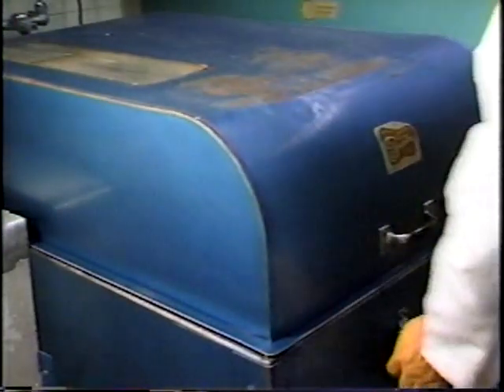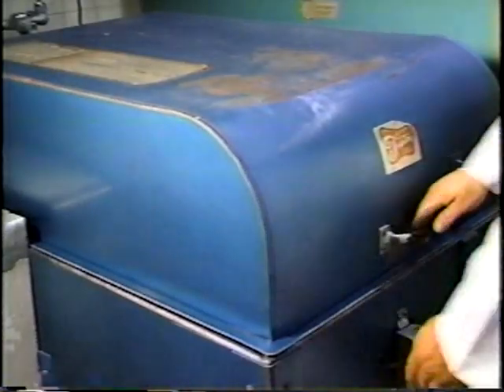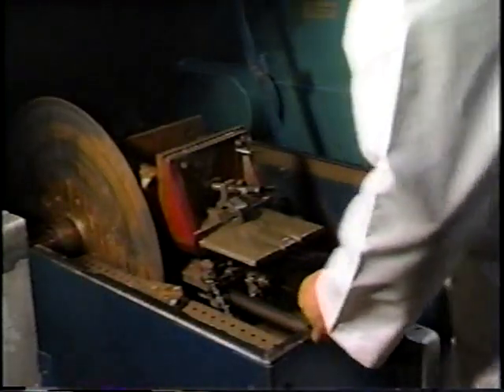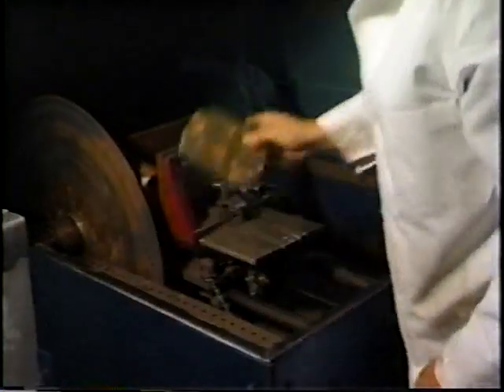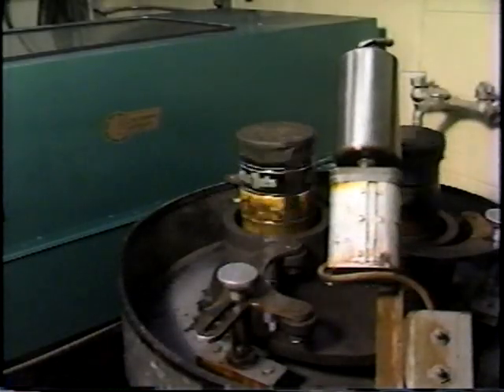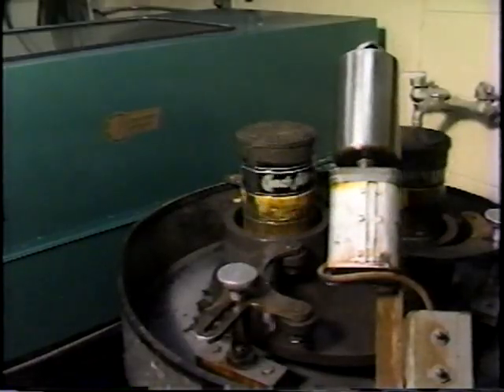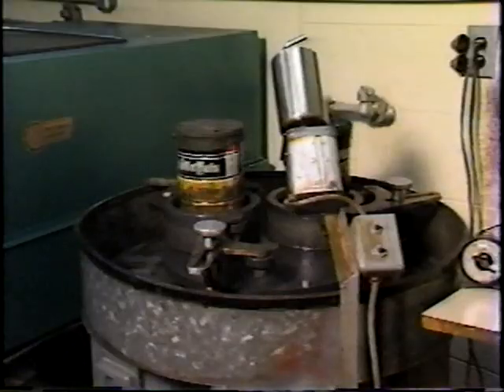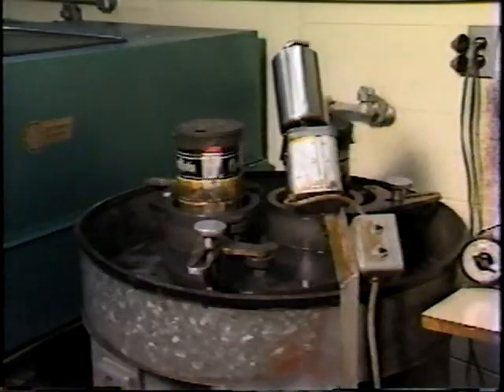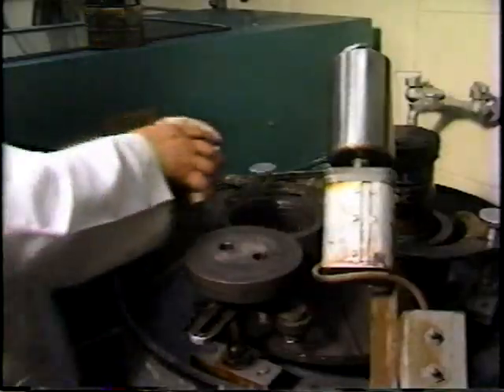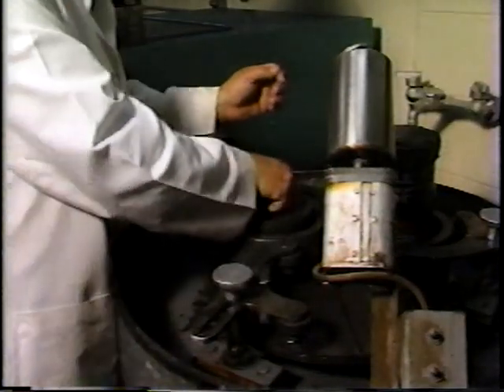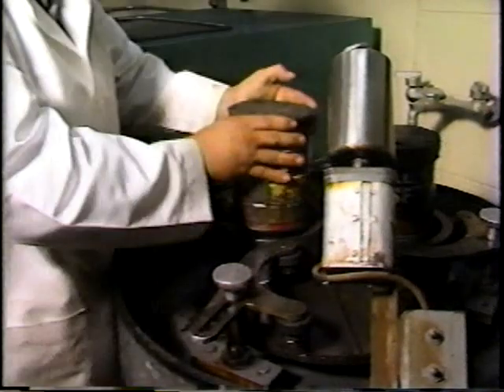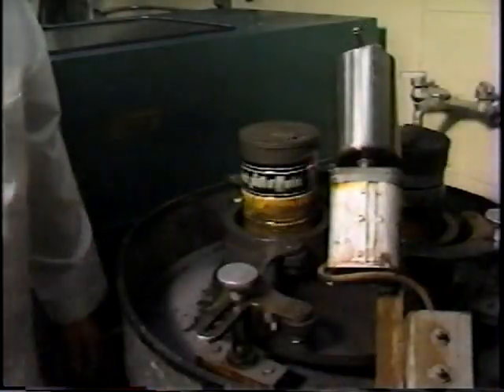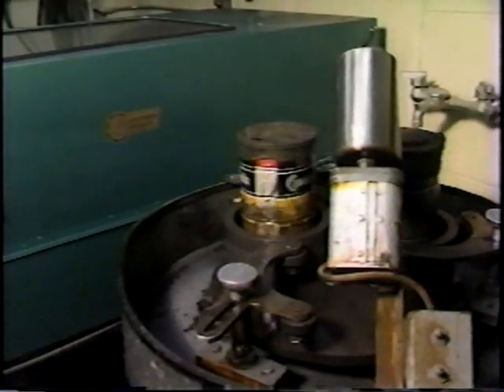For all types of petrographic examination, including air void determination, smooth slabs of concrete are cut on this large auto-feed diamond edge saw. They are then lapped on this semi-automatic equipment. We have 2 of these laps, one for the coarse grit and one for the fine. The specimens are placed inside these rings, which are held by the idler wheels on the arms. The specimens turn freely inside, and then they move over the lap so the surface is evenly ground.